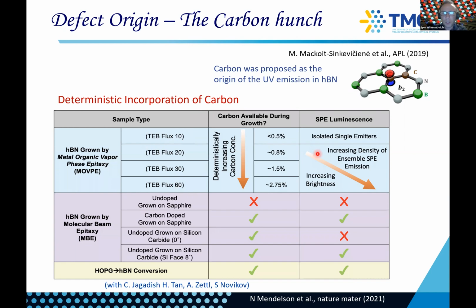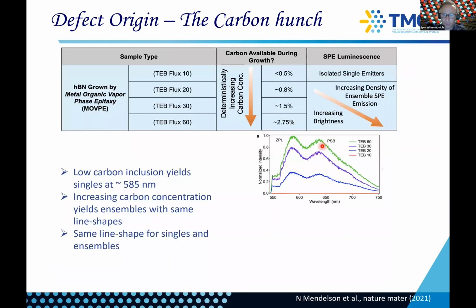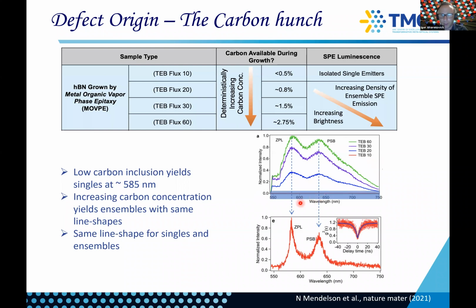And so what we found is that as we increase the carbon concentration, we see an increased emission from hBN. This is an ensemble measurement. As we go to a very low carbon concentration, about sub-percent of carbon, you basically see no emission at all with a normal optical microscope. And then we kick in our confocal microscope, and you can easily find very isolated spots that are single photon sources.